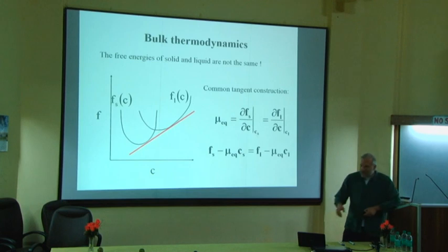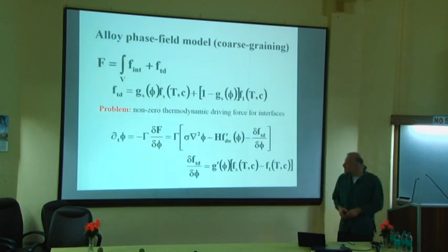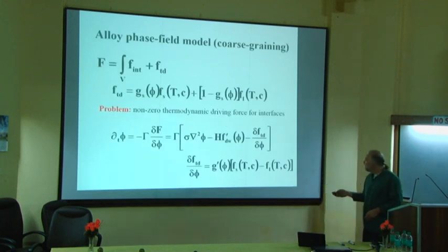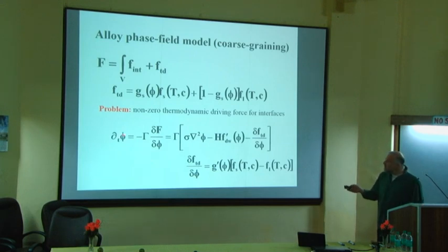Which means if you go back to this equation, in this term here, well, this factor here will not be 0, even at equilibrium. Okay? Which means that if you look at the equilibrium equation for the interface, which would correspond to dt phi equal to 0, you have these two terms, which are the traditional terms. These are the terms that give the hyperbolic tangent solution.